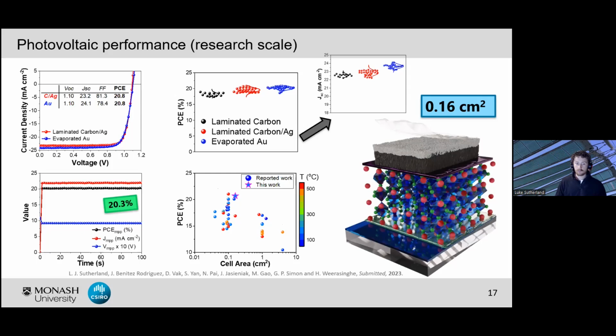But what we also see from this graph is that there's a significant drop in the power conversion efficiency once we tend towards larger area cells. So cells of 1 centimeter squared and above, we see a substantial drop going from 20% down to about 17%. Now, this is typically due to the low conductivity of carbon electrodes, which is then exacerbated at this larger cell area. But what's more, it's also due to the poor interface connection between the carbon electrode and the underlying device stack once teams progress to these larger cell areas.